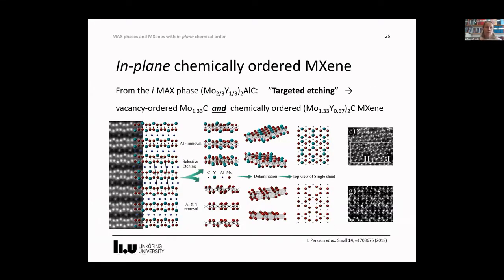i-MAX phases also enable selective elemental etching, a concept that we've called targeted etching. This means that from the same parent material, we can have either vacancy-ordered MXene by removing aluminium and yttrium in this case, or we can just remove aluminium. And these two scenarios are given by just using different etching procedures.